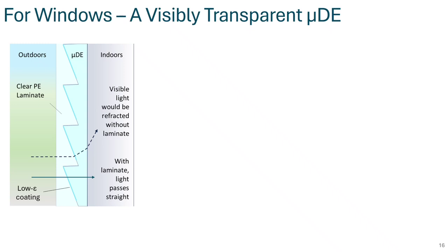We find again this micropatterned polymer, but now we replace the metal nanofilm on the tilted facet by a Low-E coating that will still exhibit the strong infrared reflectance that we are aiming for, but at the same time will show strong visible transparency, which combined to the polymer transparency results in a transparent directional emitter.